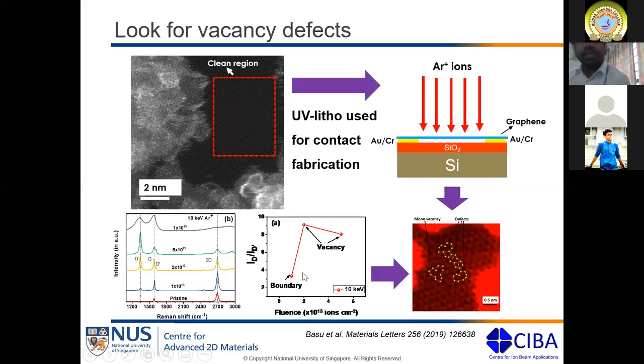And these are the Raman spectroscopic studies where you can quantify the number of defects created, and you can measure the distance between two defects. So these are all from the broad beam exposure point of view. But the problem with broad beam exposure is that you don't have much control over the structures that you create, and you don't have much control over the damage that you create.